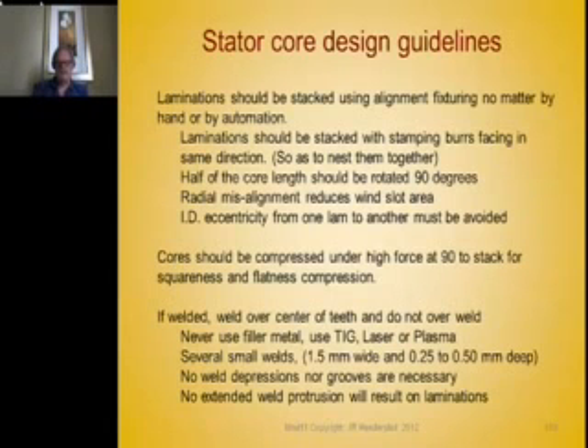If there's any misalignment of the laminations with respect to the slots, radially I mean, then that reduces your winding slot area. There shouldn't be any eccentricities between the ID and the OD from one lamination to the other. This is a problem too. If the alignment arbor is made too much smaller than the ID of the lamination, then the laminations are randomly located on that diameter. So you wind up with a rotor or a stator that's much smaller in diameter than the punched lamination diameter, and that should be avoided. Expanding arbors should be used to locate laminations for stacking. It's very important. I've seen lots of lousy stacked cores.